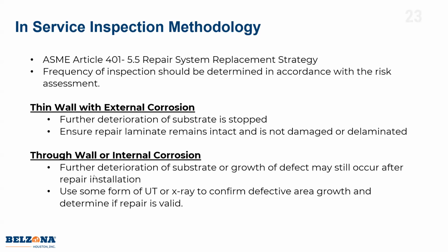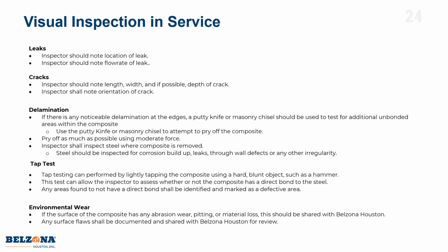For through wall or internal corrosion, further deterioration of the substrate or growth of the defect may still occur after we install the repair. So to extend the repair lifetime or inspection interval, we want to get some sort of X-ray or UT or corrosion data to confirm that, hey, we designed for a half-inch hole 5 years ago. Is that hole still a half inch? Or is that hole now an inch? Or, hey, we designed this 10 years ago, and at that time we had 10 inches of corrosion. Can we do an X-ray now and make sure the corrosion hasn't extended past this area? That's where a more quantitative inspection comes into play.